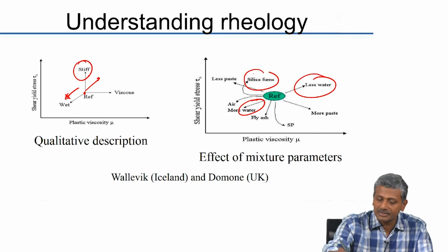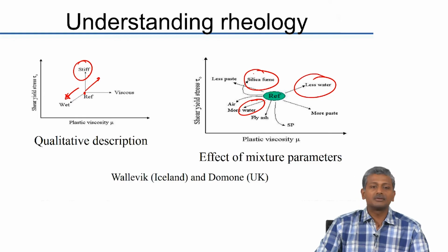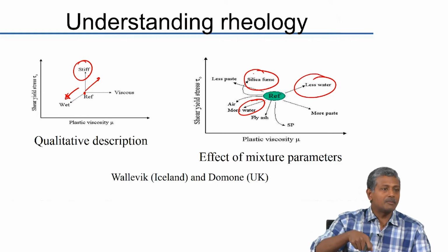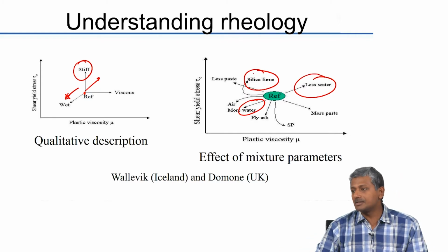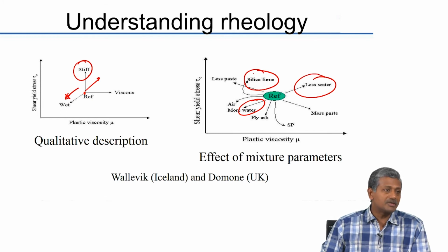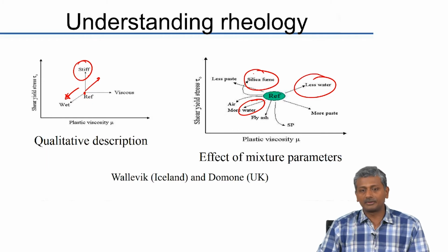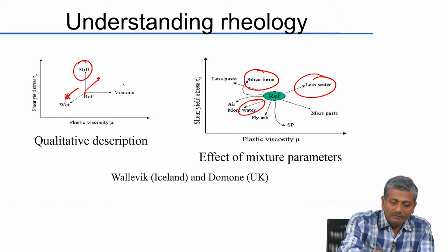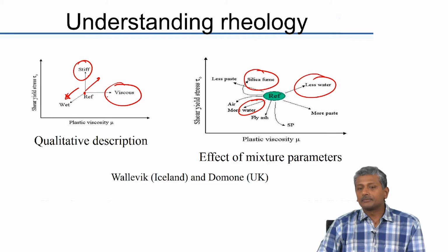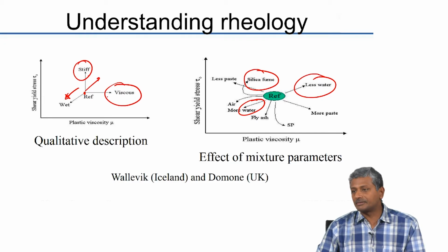Mostly what you will have is when cement is replaced with silica fume, you might see that your mix starts losing slump, but once you vibrate this mix, it is able to flow as easily as your regular cementitious mix. Okay. So, stiffer mixes typically mean greater yield stress and similar plastic viscosity. Okay. Now, a viscous mix is when you increase the plastic viscosity without really affecting the yield stress.